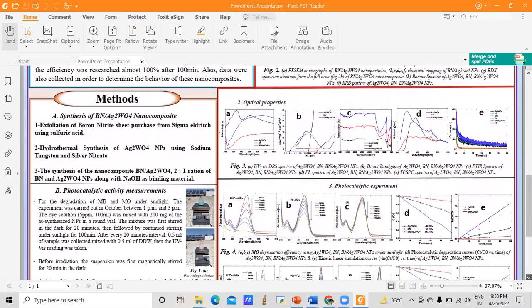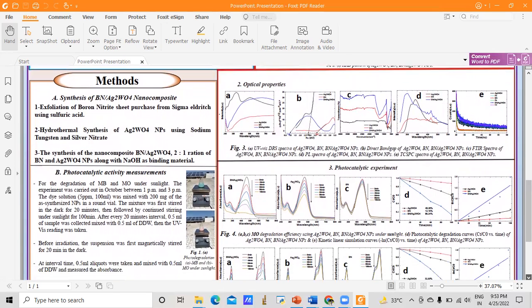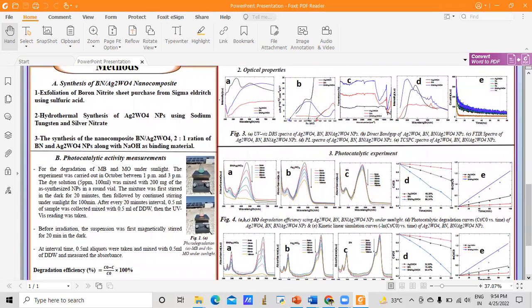So for the photocatalytic activity measurements under sunlight, the experiment was carried out in October between 1 p.m. and 3 p.m. Then the dye solution, 5 ppm and 100 ml, was mixed with 200 mg of the synthesized nanoparticles. Then the mixture was stirred in the dark for 20 minutes, followed by continued stirring under sunlight for 100 minutes. And then after every 20 minutes interval, 0.5 ml of sample was collected, mixed with 0.5 ml of double distilled water. Then the UV visible